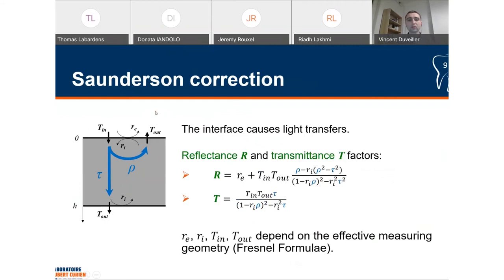These light transfers are accounted for by the Saunderson correction, which gives the measured reflectance factor denoted R and the measured transmittance factor denoted T as a function of the intrinsic reflectance and transmittance. The parameters for the Saunderson correction depend on the optical index of the material and also on the effective measuring geometry. This is why it's very important to precisely analyze the effective measuring geometry, as I will show you later.